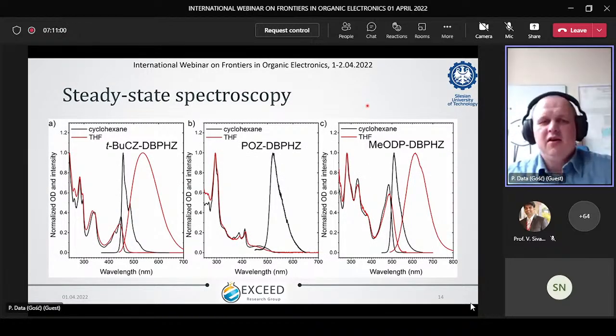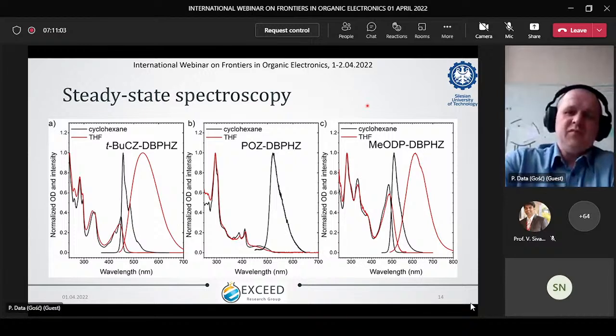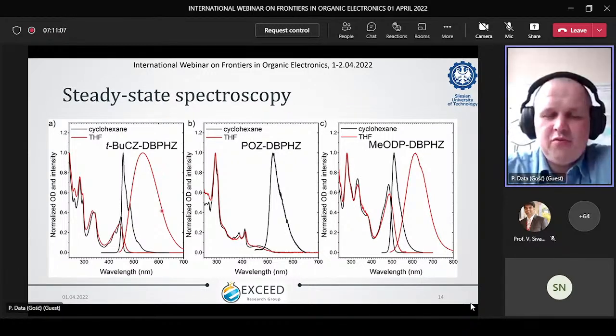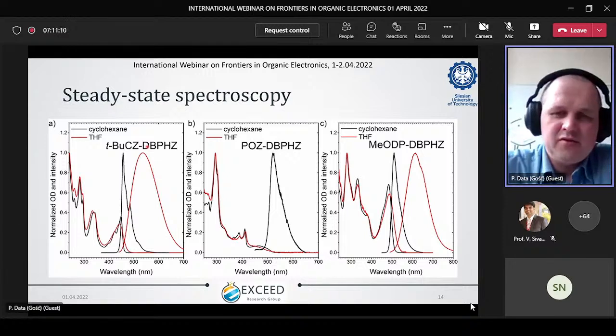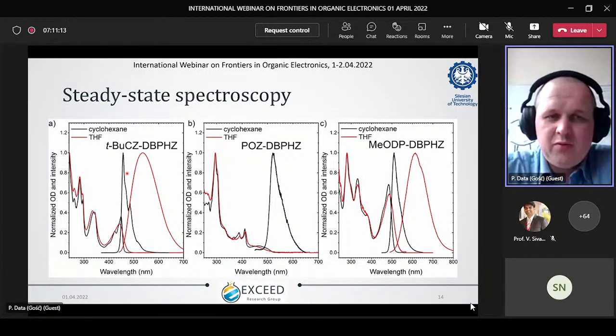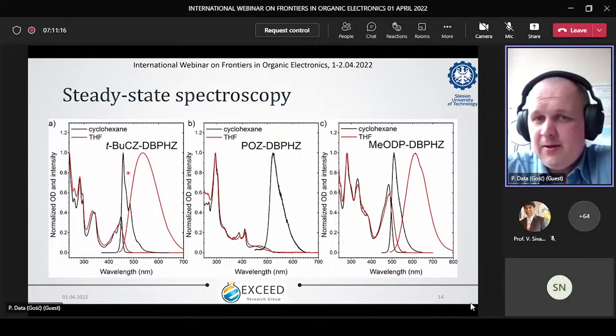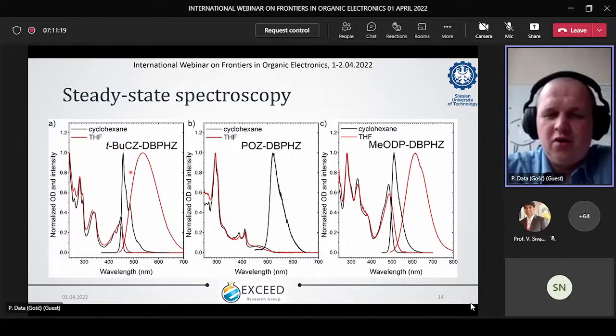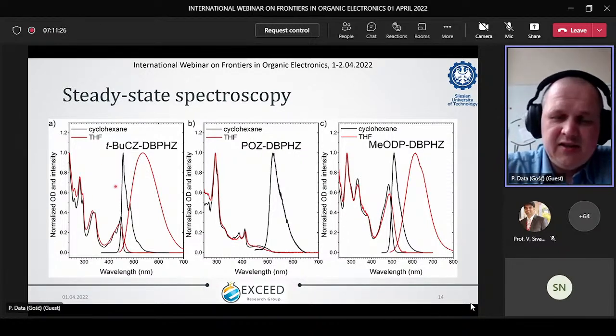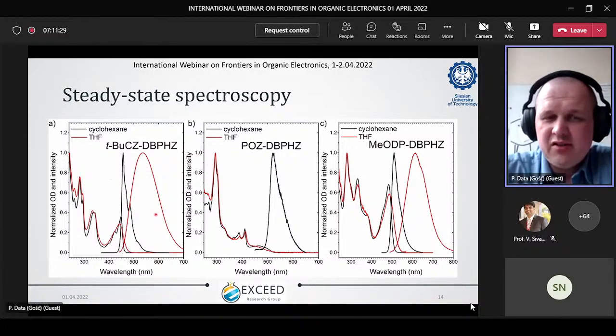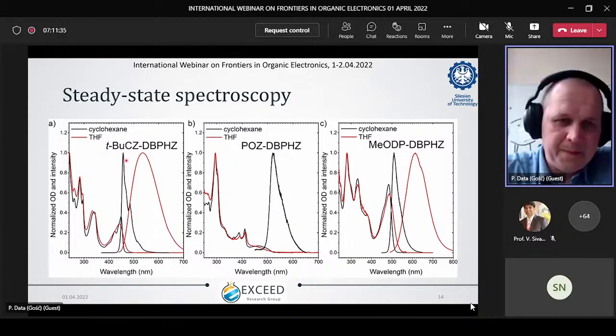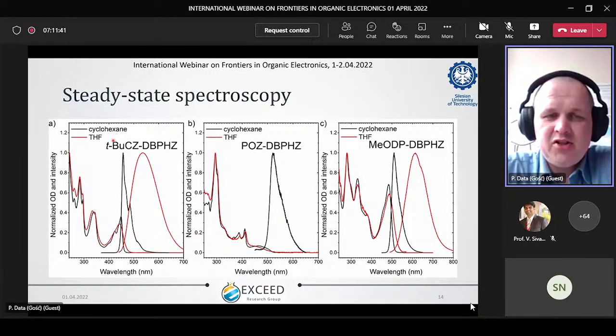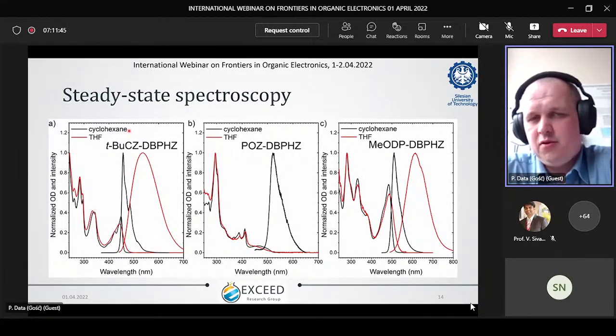The other factor is simple emission spectroscopy. So we are checking how emissive our compound is, how strong. So we can also do the PLQY, like I said before. But what is more important in the case of typical CT-based TADF emitters, we want to know if there is an actual CT state, because we have donor and acceptor molecules, and the CT, like in phosphorescence, is boosting or increasing the speed of the reverse intersystem crossing process. And how to check using typical fluorescence spectroscopy? Simple, by checking how the molecule behaves in polar and non-polar solvent.